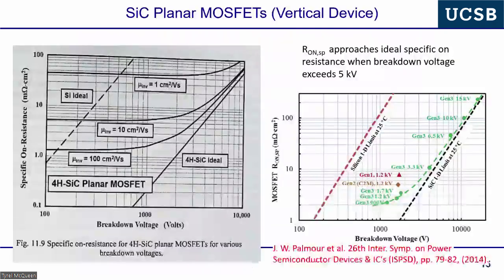Another takeaway message, when you see plots like this, here's a typical scatter plot of different generations of silicon carbide MOSFETs, looking at the on resistance and its dependence on breakdown voltage. People will throw all their data points on this, and you'll see plots populated with all the data points in the literature. Typically, they will always be far away from the predicted performance, okay? But the reason, and this is a very nice paper from the late, great John Palmour from Cree, which became Wolfspeed, is that you can actually take into account the access resistance, not the drift region resistance.